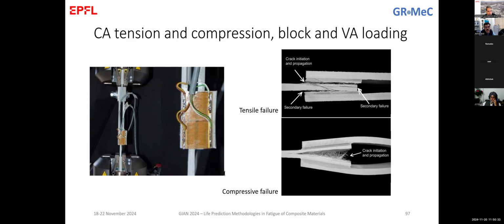I will respond in a different way. The specimen that we tested in fatigue, the idea was to avoid any buckling. So the specimen in fatigue had already a smaller material here. The tensile specimen was longer. So the tensile specimen, if I draw it here in the same way, it was like that. It was fixed here. And for compression, we avoid buckling here. And we didn't also have failure in this area because of buckling. So it buckled here, but it didn't fail.